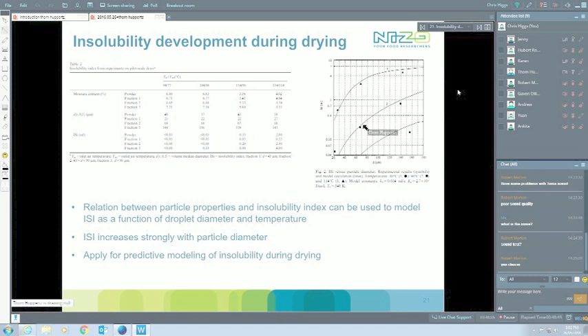Whereas the smaller powder particles don't suffer as much from it. But of course, they give us other issues. We saw earlier that they have higher free fat. We see as well that they can be difficult to dissolve quite simply from the perspective of a very high surface area, so we need to be careful with that. But the nice thing you can do once you start making these relations is effectively start modeling what my powder particle size and my different temperatures will do, and start predicting insolubility development in systems like that.